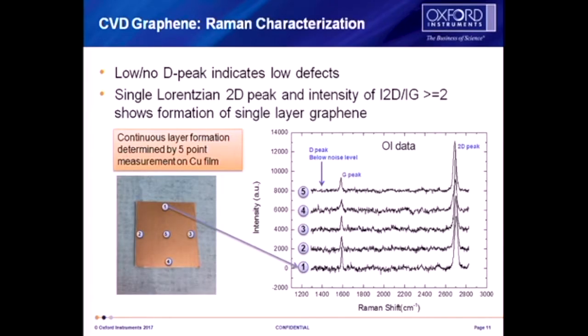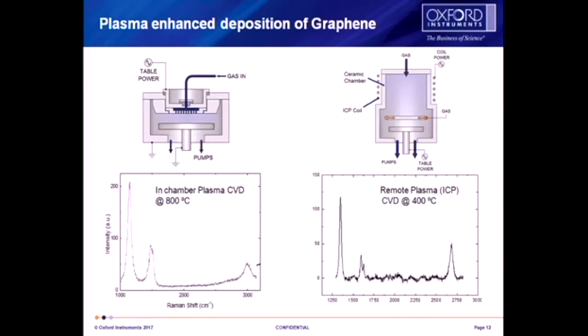And, oh, sorry, let me just go down. And you can see, this is some work we did with Southampton University 3 or 4 years ago. You can see there are quite high D peaks, a lot of defects, but that doesn't really matter so much if it actually achieves what you want it to achieve. It gives you good functionality and good electrical properties. It's not as good as the graphene you've got.